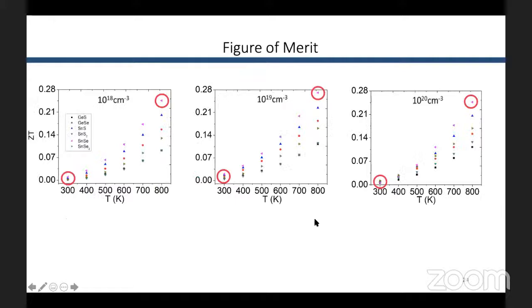However, combining all the calculated thermal and electrical properties, we can obtain what I mentioned before, the dimensionless ZT, of course, as a function of temperature. And among all of the 2D materials studied from 300 Kelvin to 800 Kelvin, the best figure of merit value was for tin selenide, regardless of doping level. In all doping levels it was the same result. Tin selenide was the best.